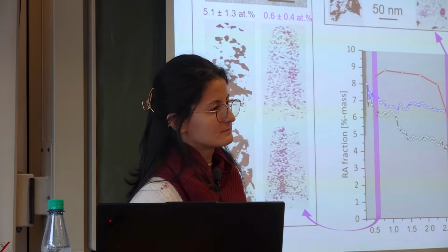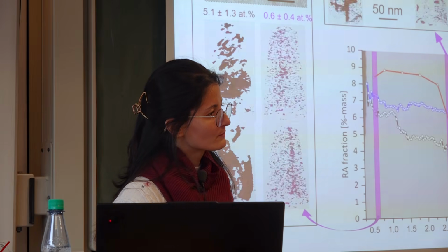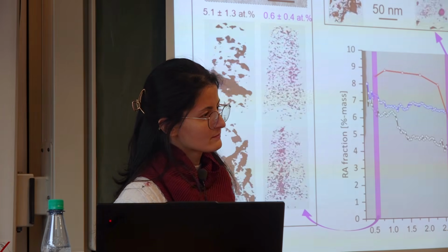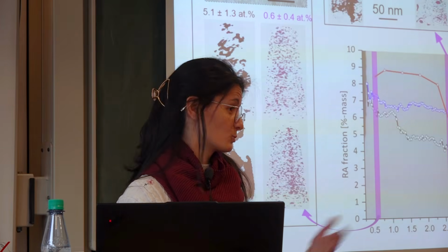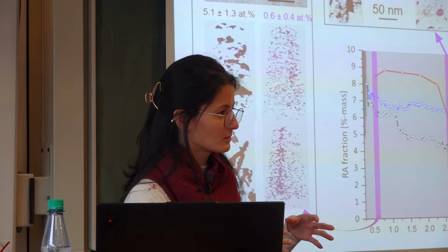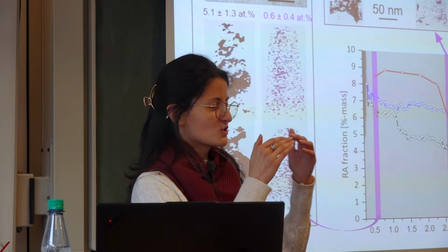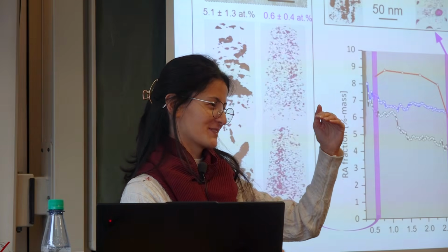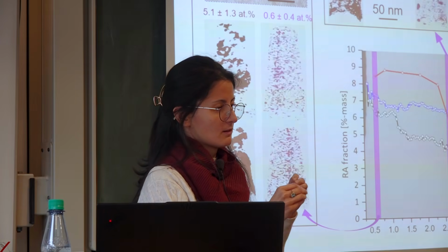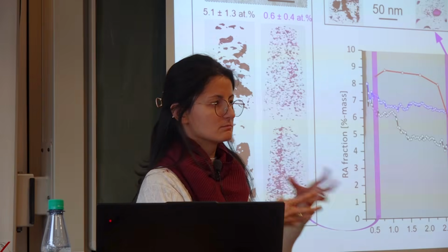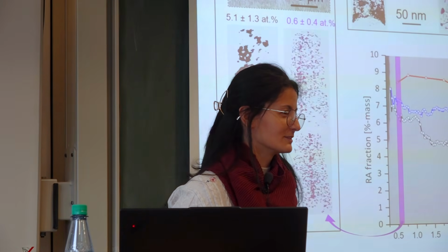If you have, like, copper there, and the other thing is carbon or something, then one of them will evaporate faster than the other. So you will not get this really shape like cutting off layer by layer, but you will have some deformation. Yeah, this is one type of artifact. If we have a heterogeneous sample, we can have one phase that is evaporated faster. It won't be in such a case that we will have 10 nanometers of difference. It would never be the case because the samples are still so small that the electric conductivity is still happening. So even 1 nanometer would not happen. But yeah.